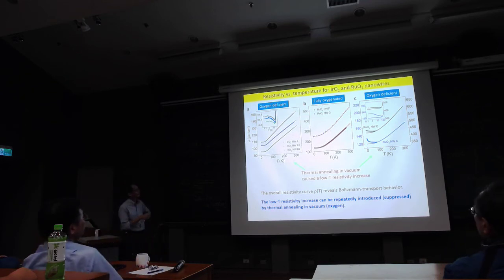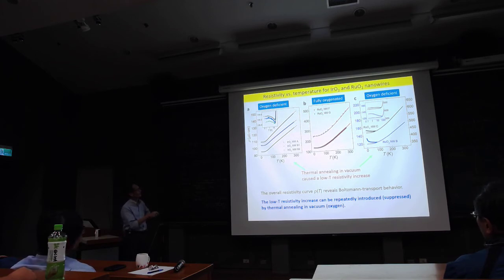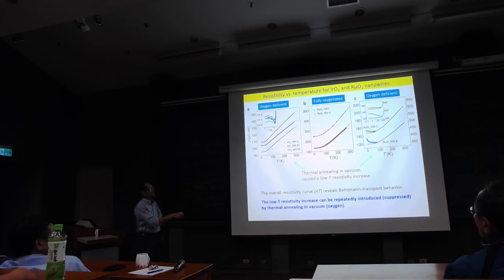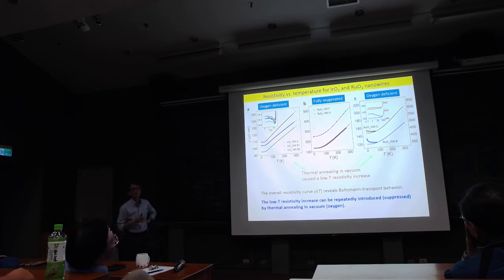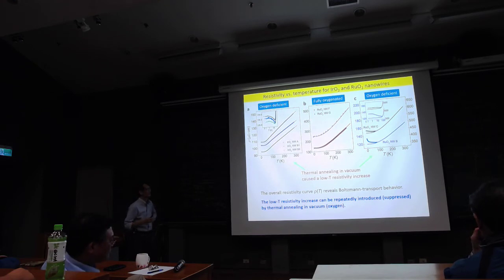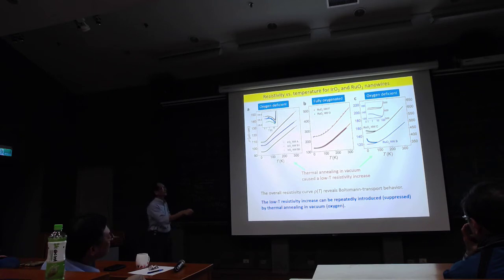So if we take oxygen out in iridium dioxide nanowire, if you look carefully or on a large scale, you see that at low temperature resistivity increases. Here is a constant, and here it increases. And also in ruthenium dioxide, if you take some oxygen out, at low temperatures you can also see a resistivity increase. So this is already some kind of indication that you have some Kondo effect. This is actually quite standard Kondo behavior, log T and then saturate.